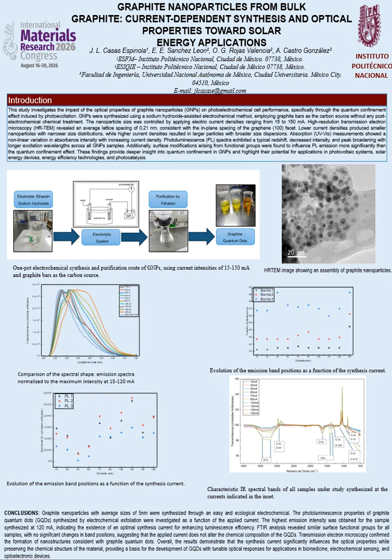In the UV-vis absorption spectra, 2 absorption bands are identified in the 200 to 320 nanometers region and 1 band in the 350 to 400 nanometers region. There are 2 peaks located around 230 and 280 nanometers, which correspond to the π-π* transitions of aromatic C=C sp2 hybridized graphitic domains, and n-π* transitions associated with oxygen-containing functional groups, such as carbonyl and carboxyl species, respectively.